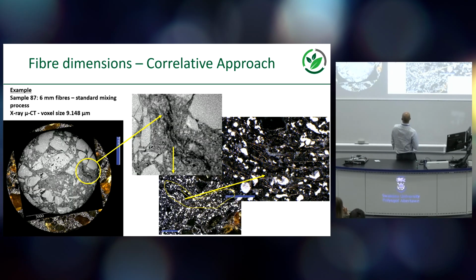And that looks something like this. So that's the region from the large area. That's what it looks like here. And then these are the actual individual fibers that you can then see embedded into that. So that allowed us to know that what we were seeing was a collection of individual fibers all stuck together, and we could correlate that back, meaning that when we looked at the rest of the volume of the material, we had a more representative idea of what was going on in the structure.